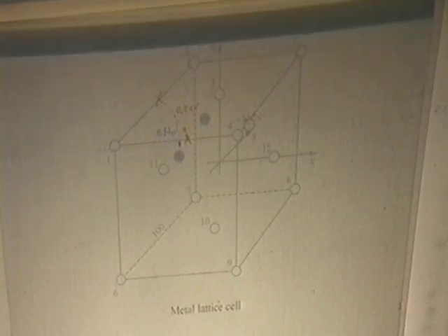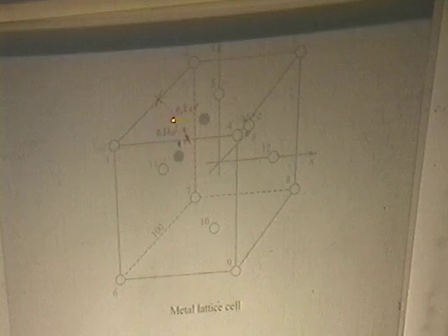Just some figures to clarify the concept. Normally, the deuterons are diffusing between octahedral sites, passing a barrier that is in the order of 0.2 electron volts, while if their energy is high enough to go inside the lattice, when the thermodynamics of the system is suitable for that, they go towards the tetrahedral site, and this barrier is higher than this one.